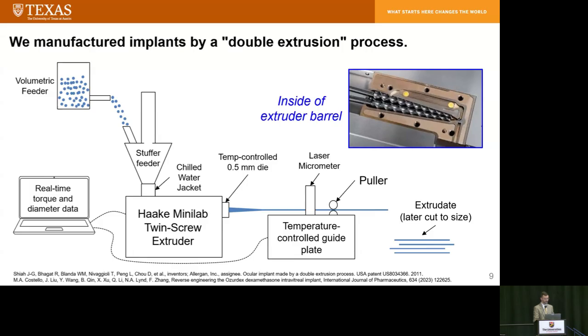So that blend is fed into the extruder. The extrusion is run at around 100 degrees Celsius, which is hot enough to melt the PLGA, but the dexamethasone does not melt. It remains crystalline throughout the process. So that mixture is then pushed through a circular die, and then the extrudate melt is drawn to the target diameter using a puller wheel.